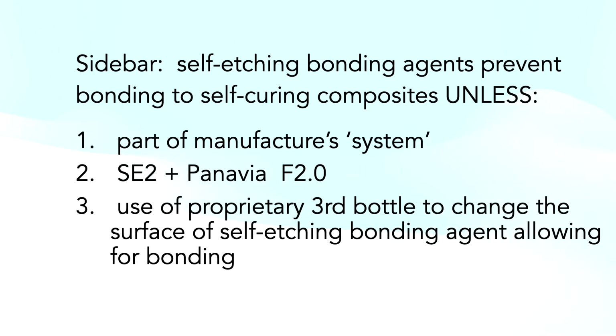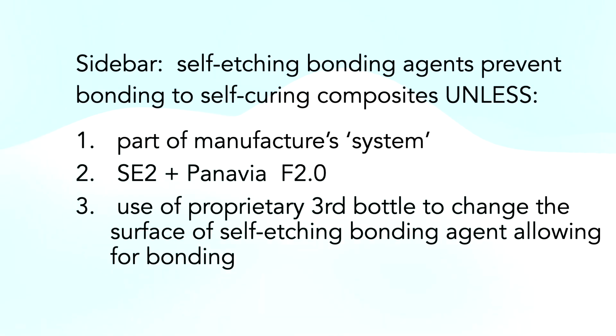So something to just keep in the back of your mental suitcase. There's a weird surface effect with self-etching bonding systems. They inhibit the attachment through polymerization of dual cure buildup materials. Okay, let me say that again. When you're using a self-etching bonding system, you have a surface that's oxygen inhibited, non-polymerized. If you try and put a dual cure buildup material on top of that, it won't adhere due to some interface chemistry, unless you're buying a system from the manufacturer where they've already figured that out, or you're using a third bottle to your 2-bottle self-etching system that negates that surface effect.